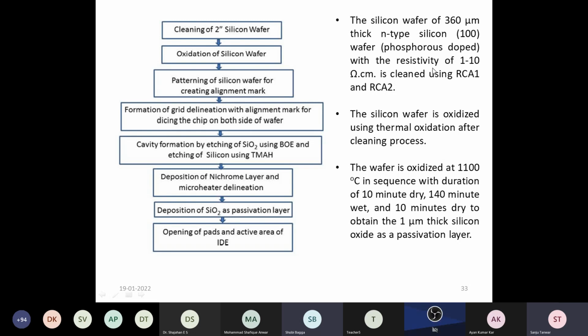N-type silicon which has the resistivity of 1 to 10 ohm centimeter is cleaned first using the RCA1 and RCA2. Then second one, it is oxidized using thermal oxidation. For the oxidation, we use both dry oxidation and wet oxidation. This is oxidized at 1100 degree centigrade for a duration of 10 minutes dry, 140 minutes wet and 10 minutes dry. Why have we used this?